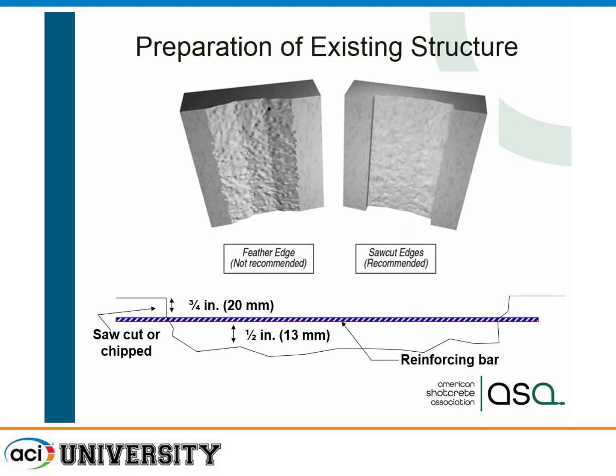We don't like feathered edges. We like to have a saw cut, 3/4 of an inch, get back behind the steel. Why would we not like a feather edge? How about anybody here do a feather edge in your repair? That's the first place to fail. It goes through a summer-winter cycle, and a little bit falls off, and then a little bit more and a little bit more. If you have a nice shoulder like this and shotcrete against it, it gives it enough meat that it can hang in there and act as a structural repair.